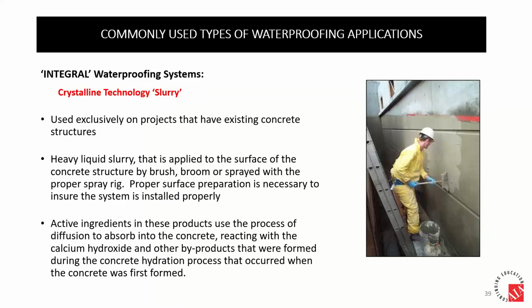Crystalline can also be applied as what we call a slurry. So it's mixed into a cementitious mix within a pail or a bucket, and then brushed on. In this case, you can see this gentleman's using like a broom to brush this on. It's important to understand here, anytime they use a slurry, it is going to change the surface of the concrete. So in some cases, that is not acceptable.